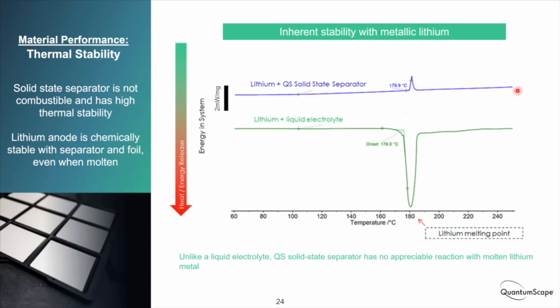In contrast, if you do the same test of lithium in contact with a liquid electrolyte, when you get to the point where lithium melts, you'll see a large exothermic reaction. This is the reaction of lithium in a liquid electrolyte. That's not surprising. But the contrast here, I think, shows that our separator is quite stable in contact with lithium. So this is going to be important from a safety point of view.